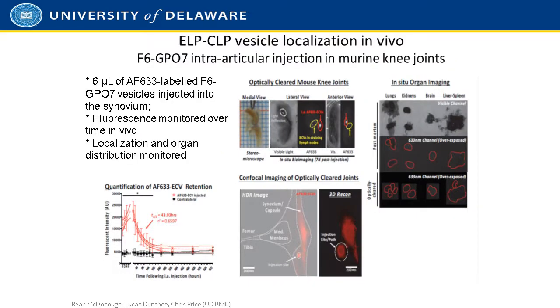We've tested the particles as well, to see if they can be retained at the knee joint in murine models. Mice have small knees, so we have to take a really small volume of fluorescently labeled vesicles, inject them in the synovium of the knee, and monitor the fluorescence over time. It might be hard to see the time points on the bottom left graph, but this was over a week, and then we looked at the localization and distribution in organs.